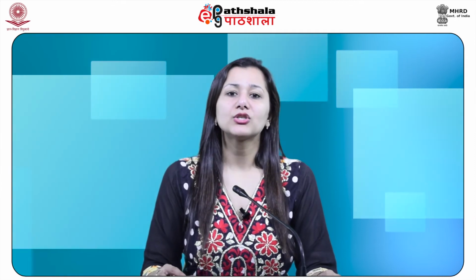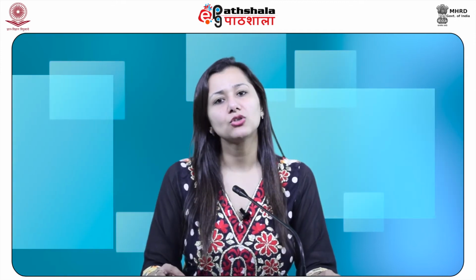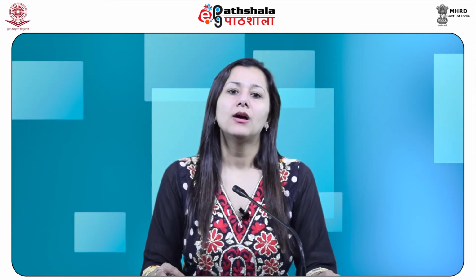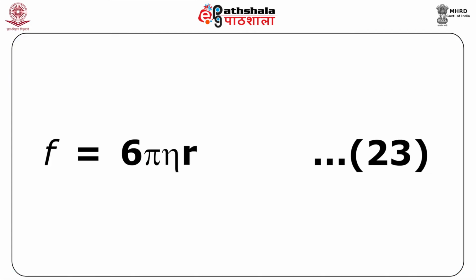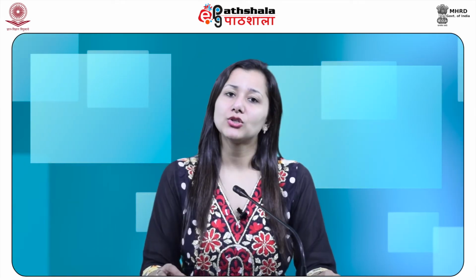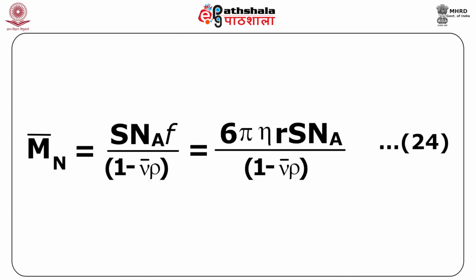For a spherical polymer particle of radius r, the frictional coefficient F is related to the coefficient of viscosity of the solvent eta by the Stokes equation, that is, F equals 6 pi eta r. This is our equation 23. Hence, from equation 22 and 23 we get Mn bar equals S Na into F divided by 1 minus V bar rho, which can be further written as 6 pi eta r S into Na divided by 1 minus V bar rho, as shown in equation 24.